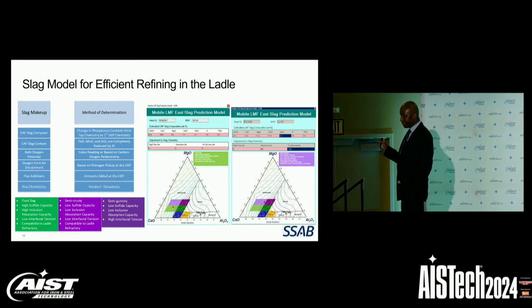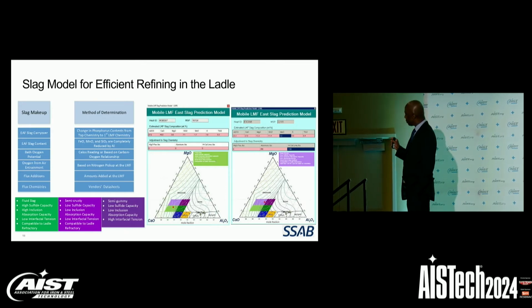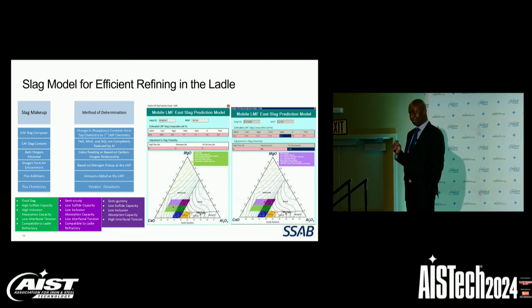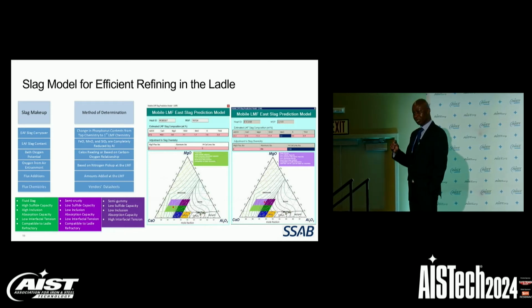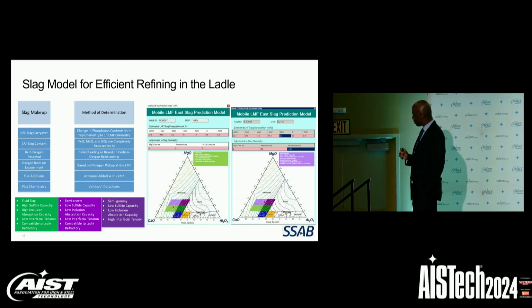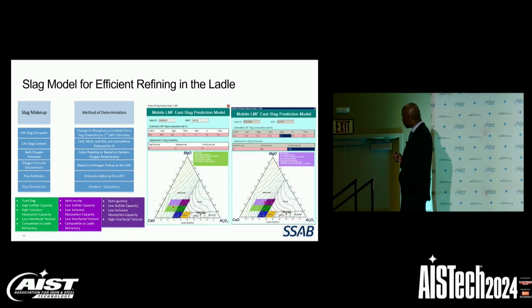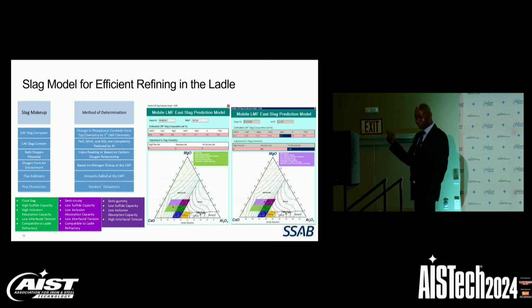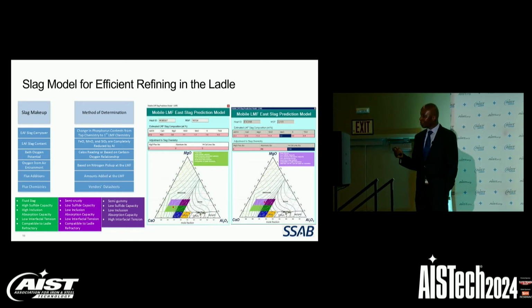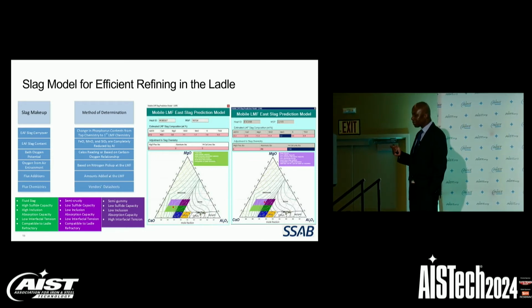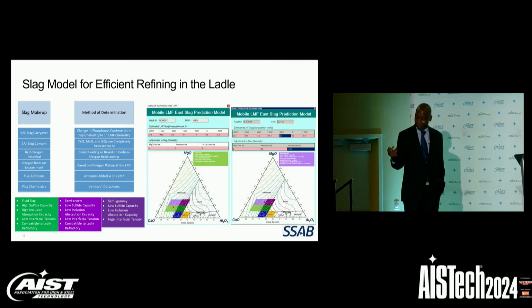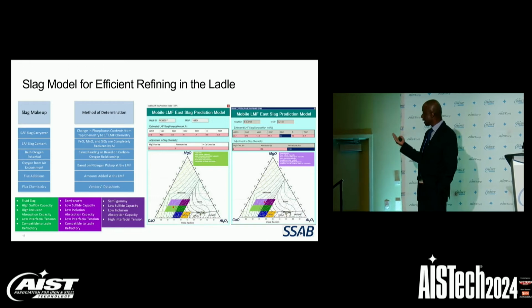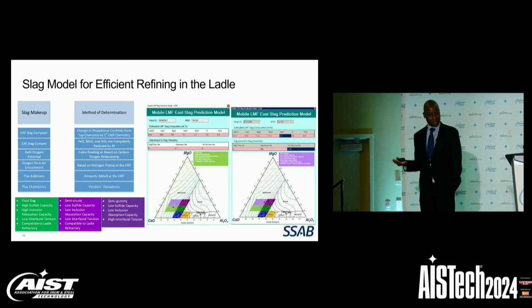What is also neat about this model is that it is able to recommend what materials to add to the slag to change it to a favorable slag condition. In this particular case, the model is recommending that some aluminum and some high-Ca lime should be added to make sure that the slag condition is changed to a favorable condition. Hence, operators can rely on this model to adjust the slag condition during refining in the ladle.